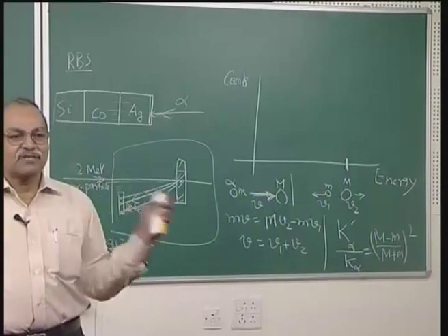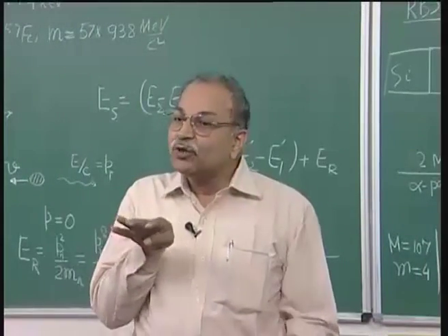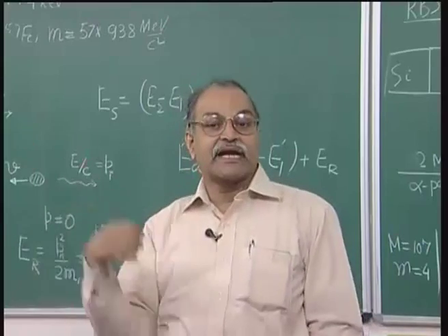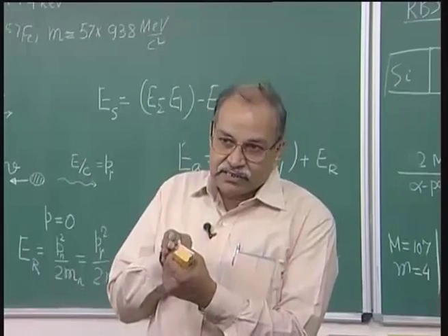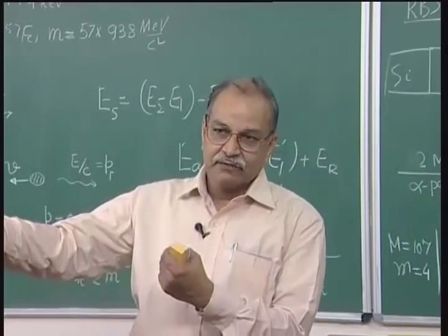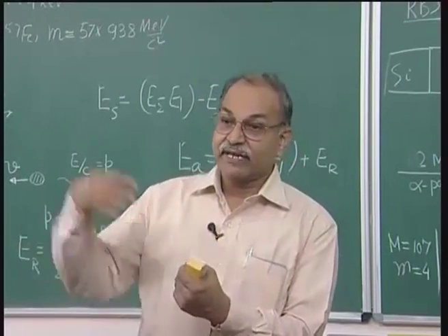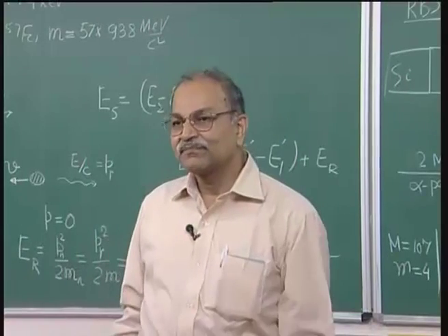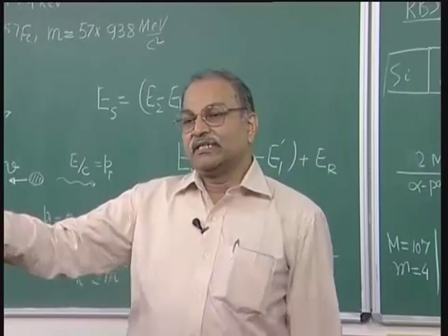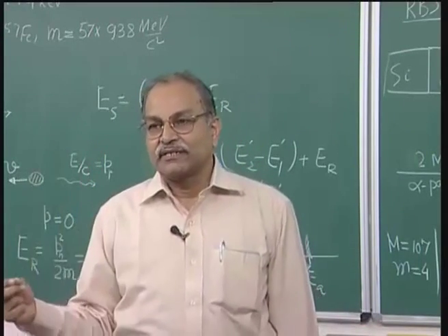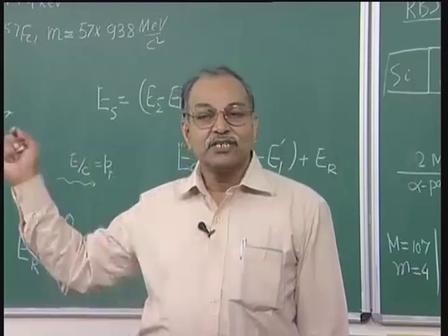Correspondingly this particle will have this energy, nothing will be more than this, no alpha particles will have energy more than this if they are scattered from the surface. If they go deeper inside and then get scattered from a silver nucleus, then during this transit into the material, they are continuously losing energy because of their interaction with all those electrons present there. So, if the nuclear encounter is at a depth, then at that encounter the incident energy is already smaller than the initial beam energy.